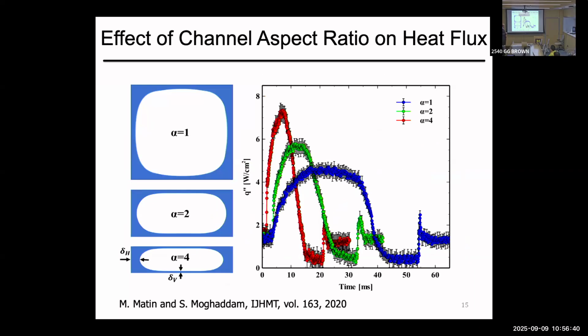Let's say we have channels with different aspect ratios. So we proved that it's a known fluid dynamic phenomenon. If you are going from a square cross section to a high aspect ratio, it's as if you are squeezing a balloon, and the force of the balloon is surface tension. So what the balloon does is fight against you. It drains these films. So high aspect ratio means thinner films.